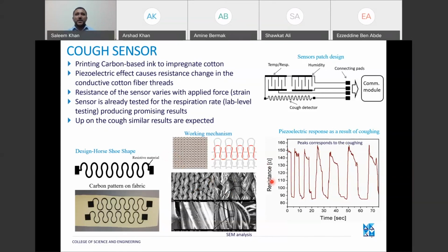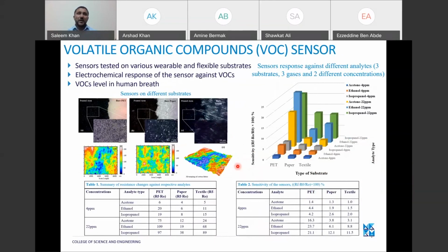Similarly, volatile organic compound sensing is really important for monitoring human breath, and as we have seen, it is also suitable for use in the smart glove. We have demonstrated these sensors on 3 different substrates, and we have tested 3 different gases, ethanol, isopropanol, and acetone, against 2 different concentrations, 4 ppm or 22 ppm, parts per million. They are really responsive, as we can see. This was a substrate comparison study, and we can see that the PET substrates have shown good promising results against these different gases. All these sensors were printed using inkjet technology, with deposition using screen printing.